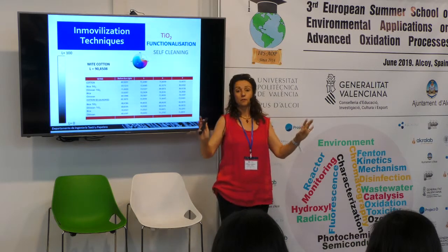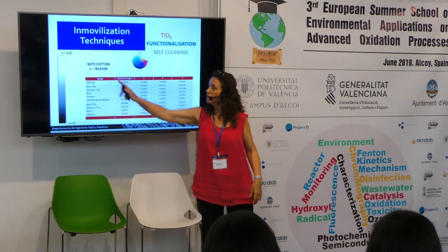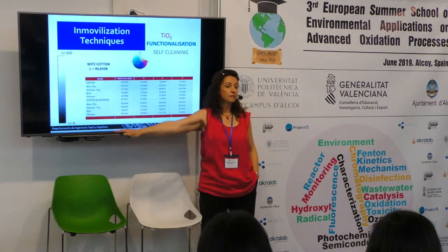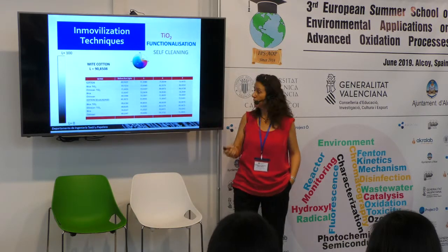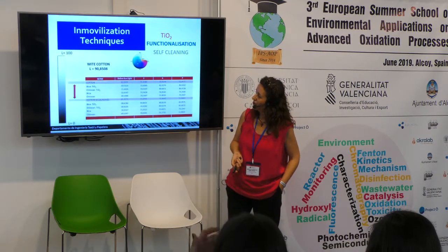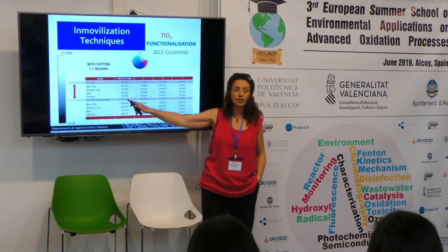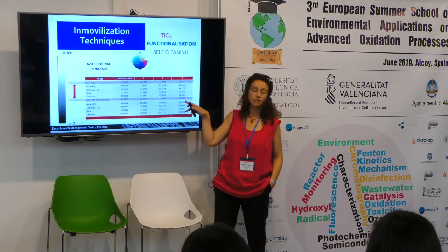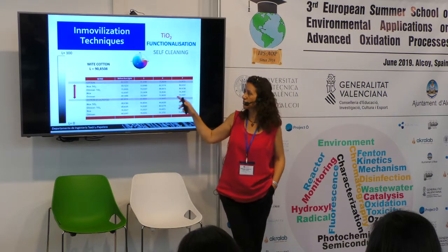And which is the effect? When I have my cloth, which is white, the L value, which moves from white to black, is 90.85. And here I've got some of the values. Look, we've got cotton and cotton with 10 laundries. It means that the values, when we have dyed with wine, or we have the stain with wine, are more or less the same.